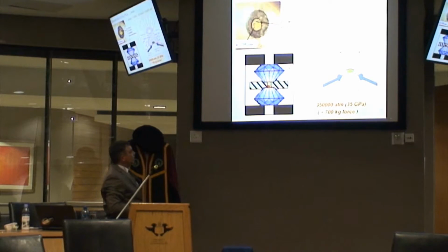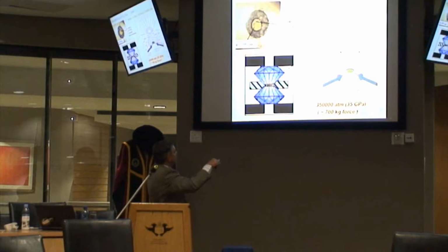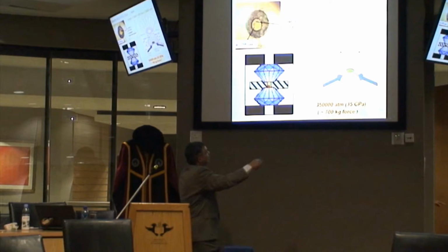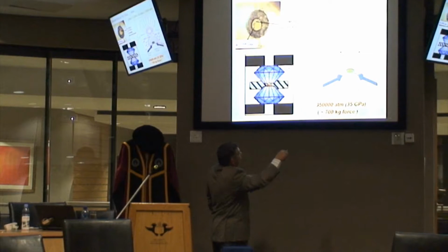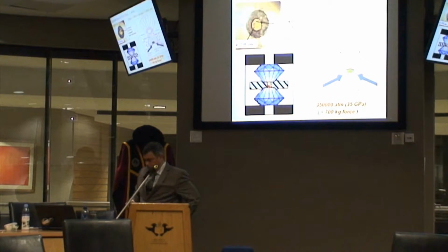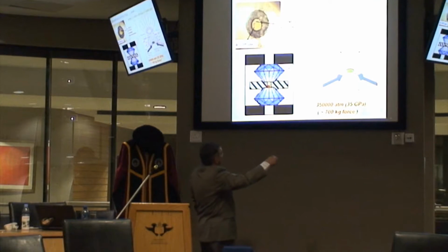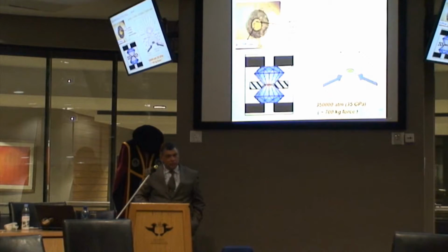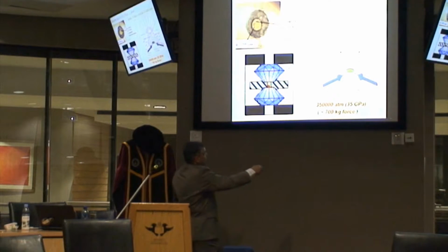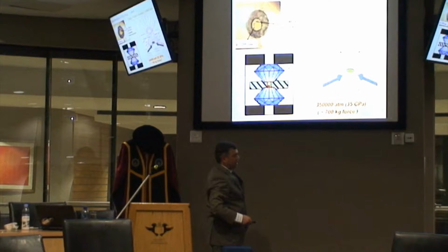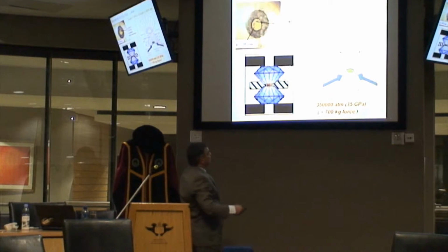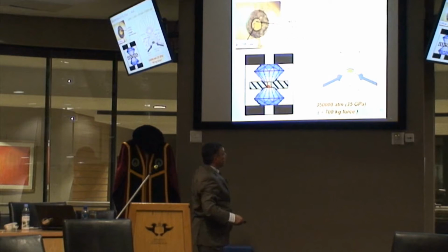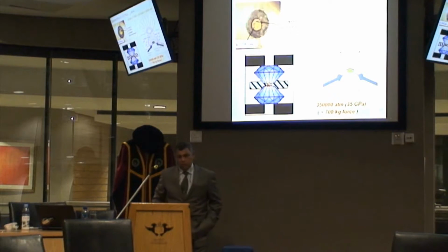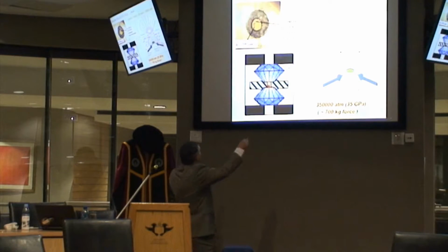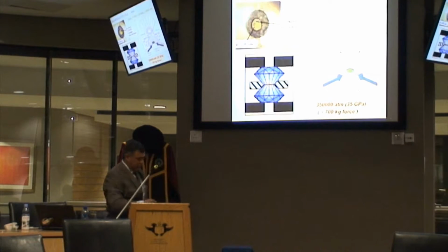Here's some further detail of how this device works. We apply a force like this to generate the pressure on the compound. These are the typical dimensions. We call this the culet. It's about half a millimeter in diameter. If we apply a force of 700 kilograms, which you can do quite readily and quite conveniently, we can generate up to 350,000 atmospheres fairly routinely. If we reduce this area, and therefore reduce the size of the cavity, with modest forces of 100 kilograms, you can get up to 1 million atmospheres. And there's a view into a cavity of a sample at 200,000 atmospheres.